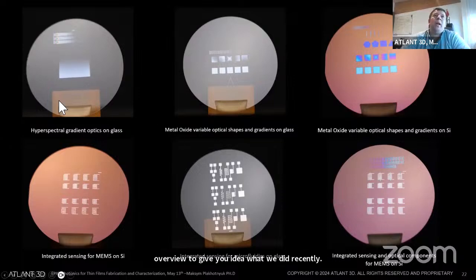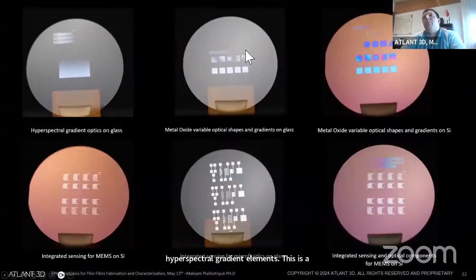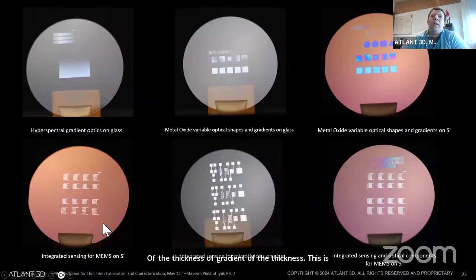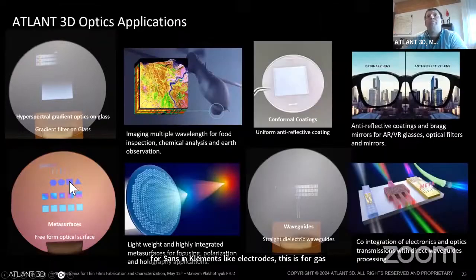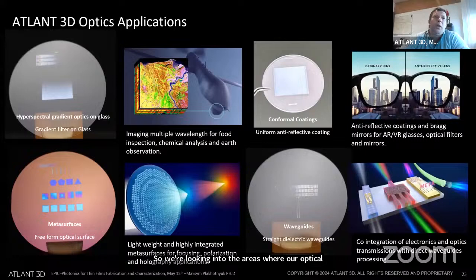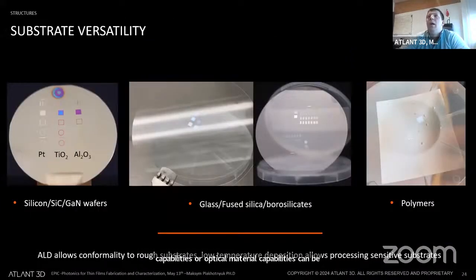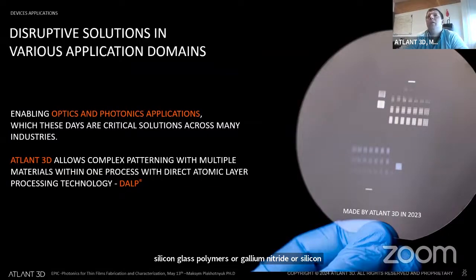So this is a direct rastered approach for hyperspectral gradient elements. These are two similar wafers that we did development with variation of the thickness, gradient of the thickness. This is for sensing elements like electrodes. This is for gas sensing. This is for electrochemistry. So we're looking into the areas where our optical material capabilities can be used, like for optical filters, or for hyperspectral, or for meta surfaces, or for waveguides. And we can work on any type of substrates, not only silicon: glass, polymers, or gallium nitride, or silicon carbide. It really doesn't matter. ALD is quite flexible in that sense. And the capabilities that we are the most interested in is optics and photonics.